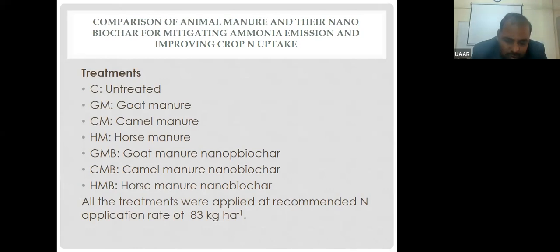Actually, their nanobiochar was prepared by grinding these samples in a ball mill and sieving them in a 2 mm mesh sieve to get these nanoparticle less than 100 nanometer in diameter.